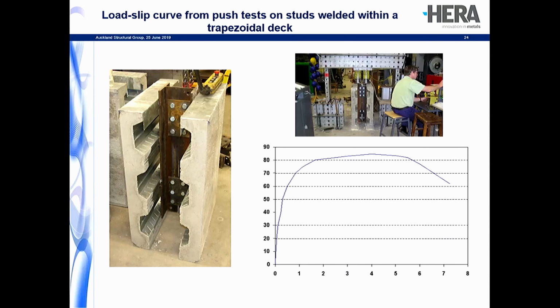And basically the history of this was that back in the early 2000s, the first trapezoidal deck was introduced from the UK into Australia, and because it was a new type of decking used there, they decided to do some push tests, similar to those which you can see in the top right-hand picture. And while we would be expecting a slip curve like this shown in blue, so you get a slip capacity of 6 millimetres, what they were actually finding was something far worse, something like that. So it was almost half the ductility that we were expecting.